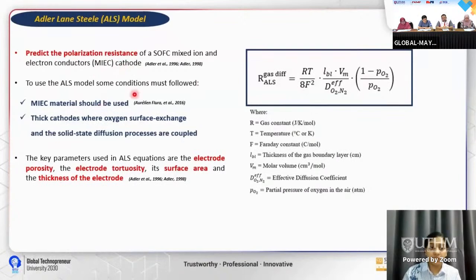So in order to use this model, there are some conditions that we have to follow. The MIEC material should be used, which is the BSCF, the cathode where oxygen surface exchange and the solid state diffusion process are coupled. The key parameters used in this ALS model will be the porosity, tortuosity, surface area and the thickness of the electrode. So this will be the main polarization resistance equation in line with the ALS model.